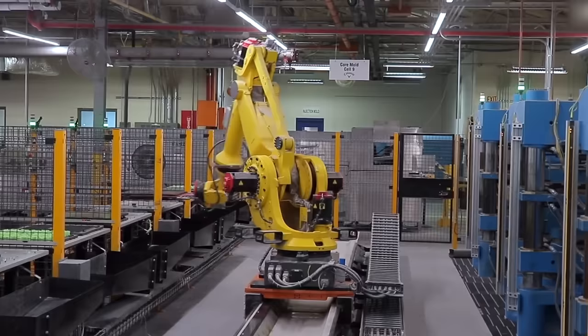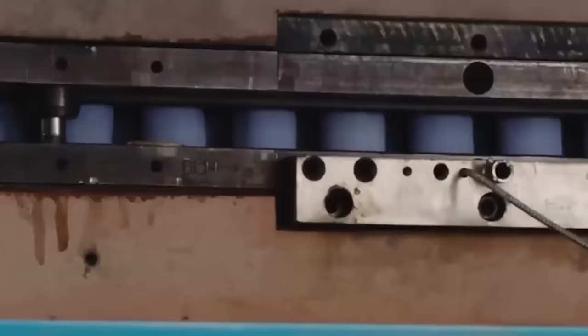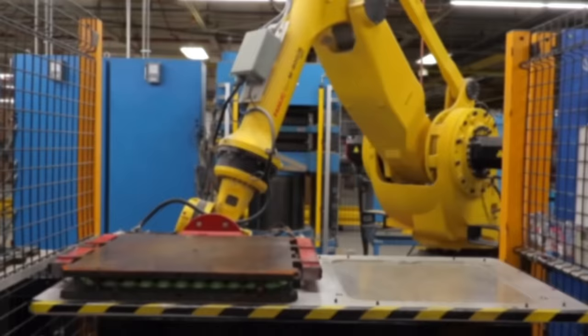The slugs then travel on a conveyor over to a compression molding machine. Here, a worker places the slugs into the steel molds. When the door closes, the bottom part of the mold presses up against the top part, applying over a ton of pressure. The newly rounded rubber is also cooking at 160 degrees Celsius. This is done for a period of 13 minutes to harden the rubber.